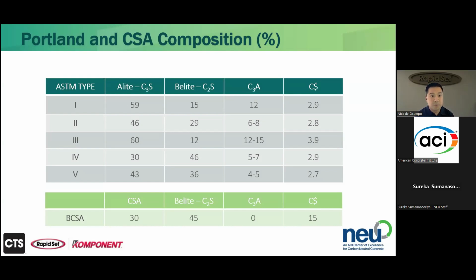If you look at the bottom for BCSA, there is no alite present. That CSA basically takes over all of that. If you remember, CSA is C4A3S, where alite is C3S. Basically, all of the calcium present in the kiln gets occupied by CSA, so there's not enough calcium to produce alite. The other reason is that alite is produced at a temperature range outside of the range of CSA and vice versa, so there's really no overlap depending on the temperature of the kiln for CSA to be produced versus alite.